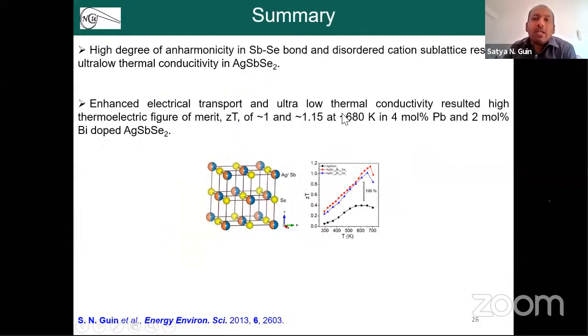So this work is actually one of the first examples in this area of ultra-low thermal conductivity, which is now gaining very much attention in the area of thermoelectrics, which shows that an ultra-low thermal conducting material could be a potential candidate to achieve a high thermoelectric figure of merit in the system. And if you look in the literature nowadays, every day you can see some paper which discusses the importance of ultra-low thermal conductivity in the area of thermoelectrics.